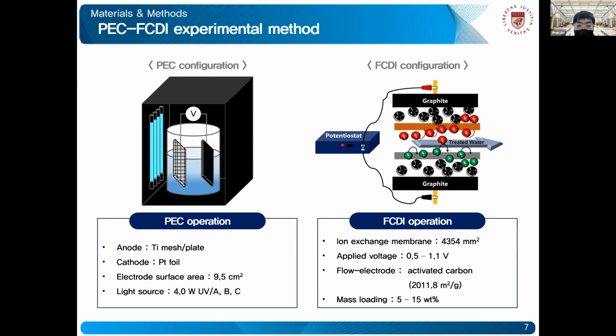The electrodes used in the PEC system were fabricated on the Ti mesh and Ti plate at 600 degrees Celsius under cathodic polarization. On the FCDI side, the ion exchange membranes used were 4354 millimeters squared, and the applied voltage was between 0.5 and 1.1 volts.